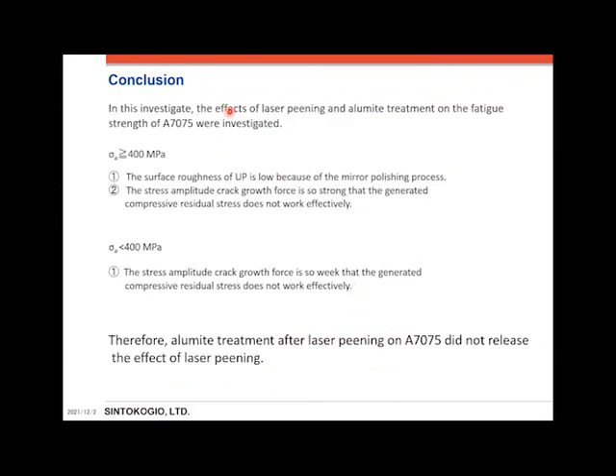So, conclusion. In this study, the effect of laser peening and alumite treatment on the fatigue strength of A7075 was investigated. The result is shown here. Therefore, alumite treatment after the laser peening on A7075 did not release the effect of laser peening.